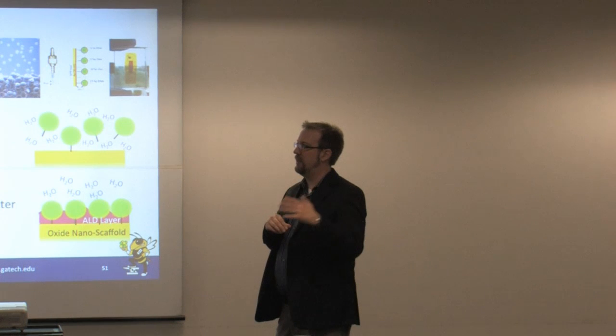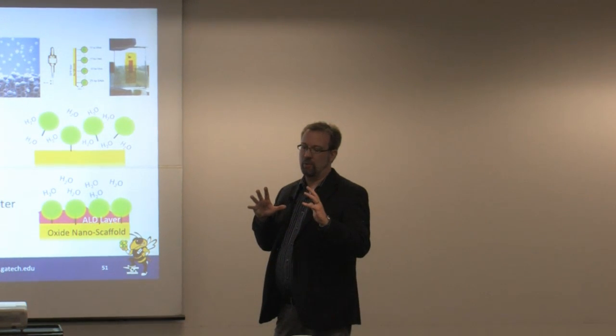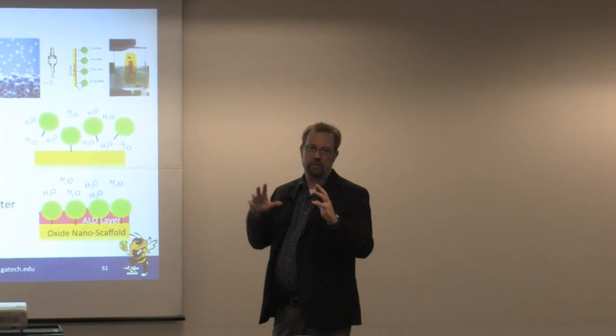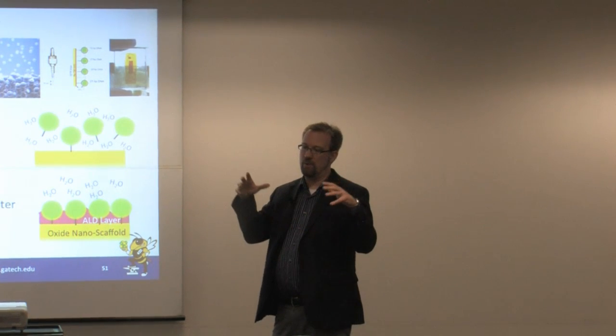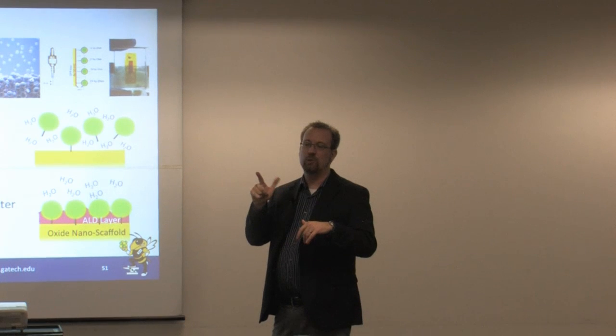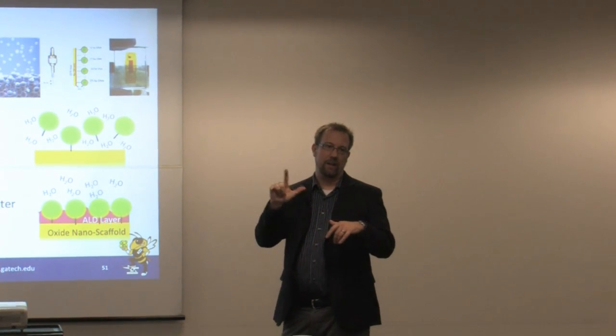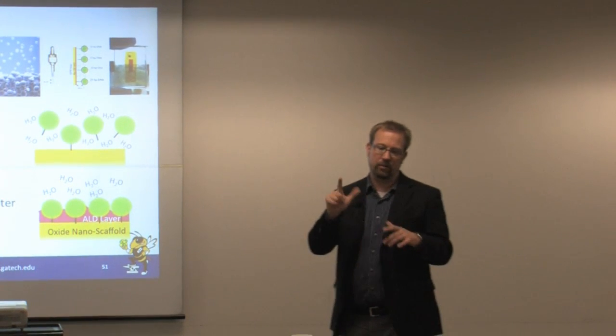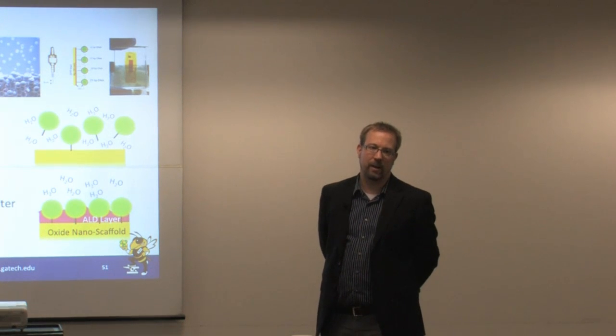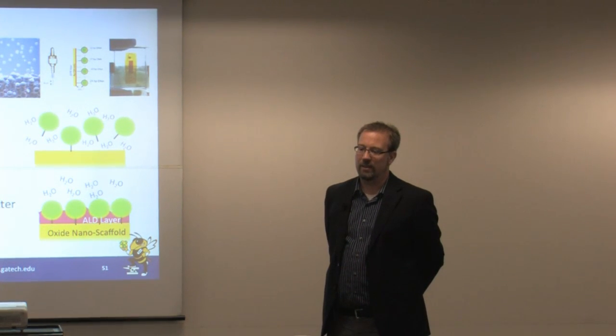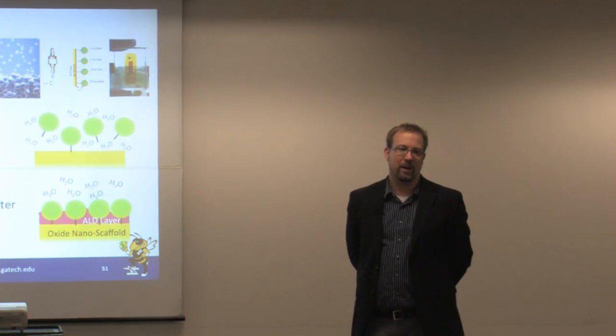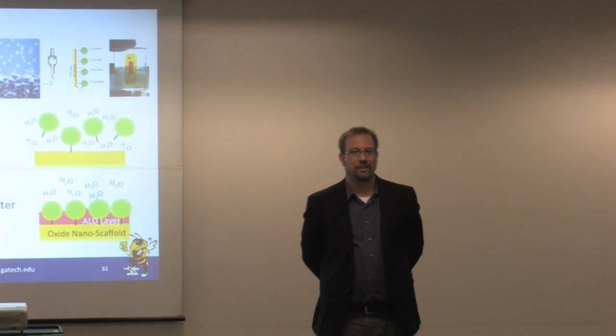And we've been working with Tim's group at Emory where they're doing SFG, sum frequency generation measurements, where they can track the spatial orientation of the molecule before and after ALD. And so we do see it's rearranging, so we're somehow modifying its position. Yeah, this is one of the things that, to me, is one of the biggest challenges. How do we characterize this structure?